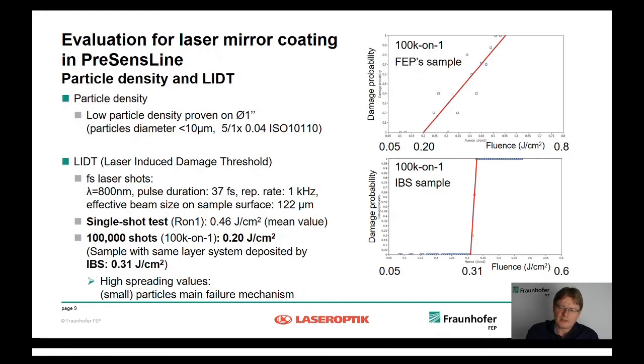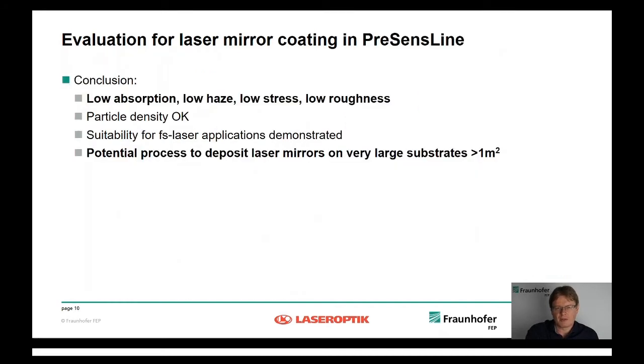We attribute this spreading of the values to some small particles still being in the layer system, which at some spots contribute to lower LIDT values. So still, we have to do something to make this better in the future. But the current status is that we observed low absorption, low haze, low stress, low roughness. Particle density was okay. We could prove the suitability for femtosecond laser applications. And so we have a potential process to deposit mirrors on very large substrates. Here I speak about 1 square meter and even bigger in the future.